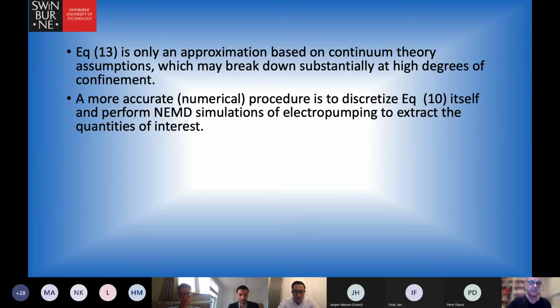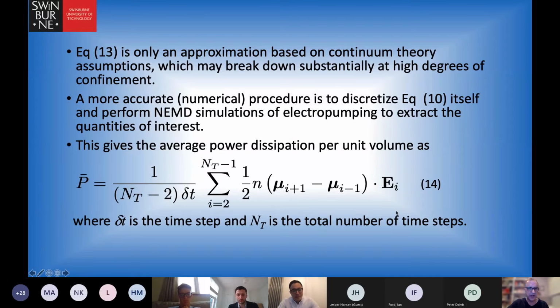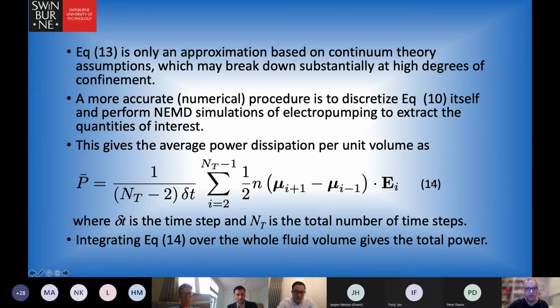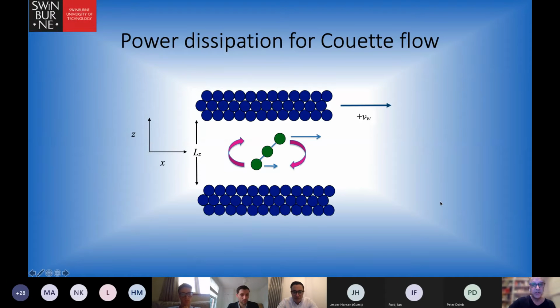So a more accurate numerical procedure would be to discretize that equation, equation 10, and perform NEMD simulations of the electropumping to extract the quantities of interest. If you do that, you get a discretized version of that expression, where NT is the total length of your simulation, delta T is your time step, and the various mu's are the dipole moments of the water molecules at various different times. If you integrate this expression over the whole fluid volume, it will give you the total power. So that's how we can do it for electropumping.